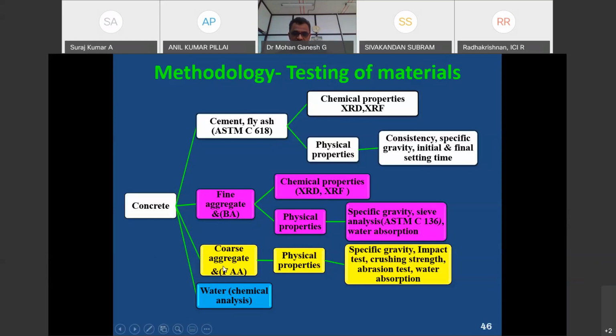And for coarse aggregate and fly ash based aggregate, again the physical properties, specific gravity, impact test. Since we manufactured the fly ash aggregate, we should know what is the impact value as well as crushing value and abrasion test. Everything we have done, and it was compared with the coarse aggregate, and we have done the water absorption also. So finally, if you are using the fly ash aggregate, it should be at par with the coarse aggregate. There should not be any deviation.